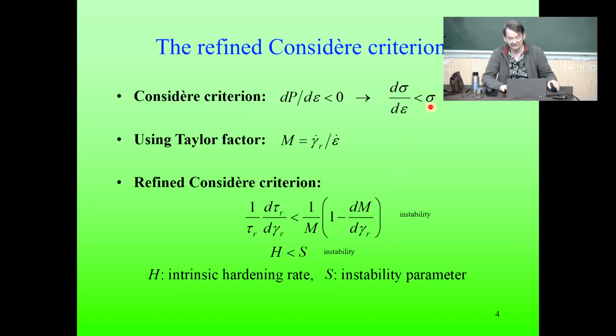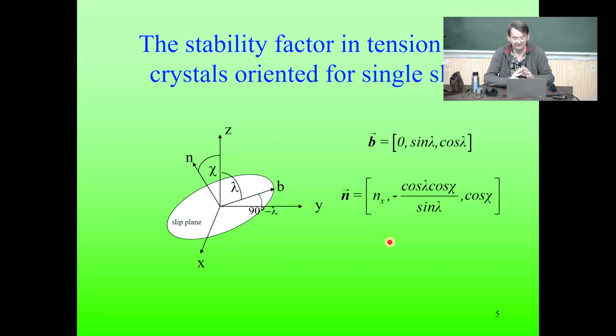So the Considère criterion can be rewritten, but now we go into a single slip here to see the effect of orientation on the stability in tensile testing. So we define the slip system with b and n like this, with two values, chi and lambda. And we do so that lambda, b and n and Z are in the same reference, b and n are in the ZY plane.